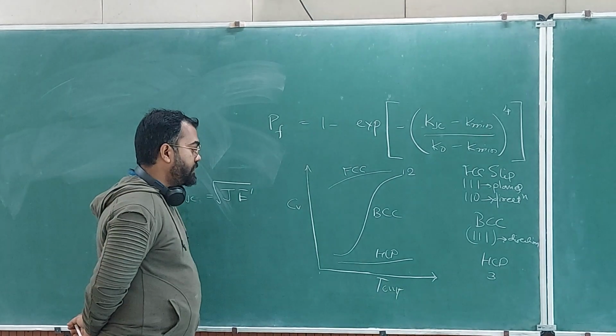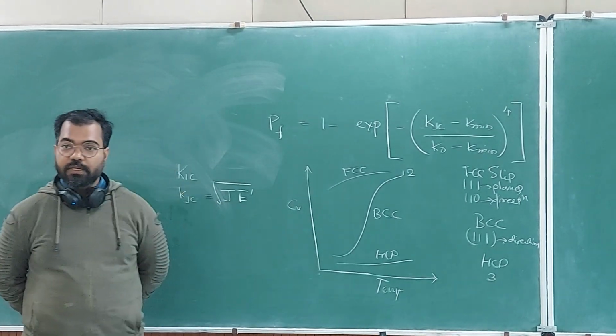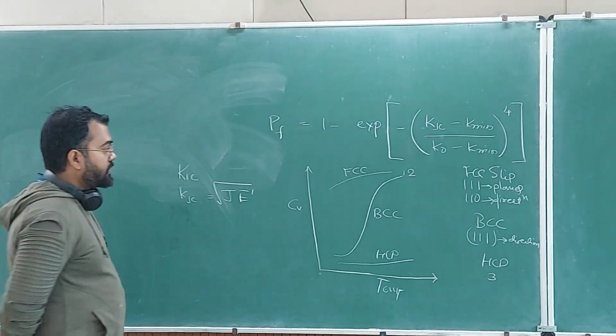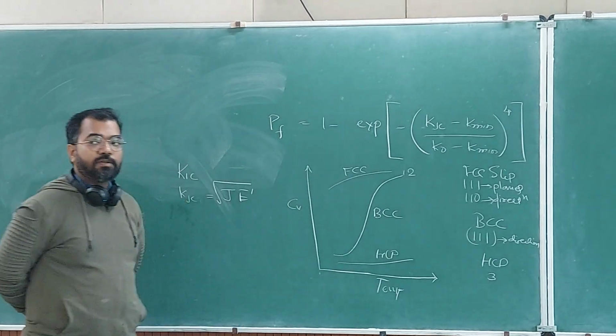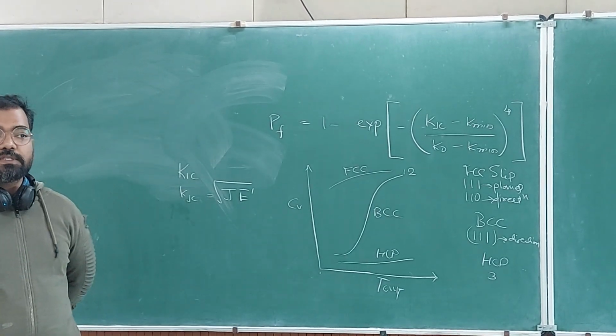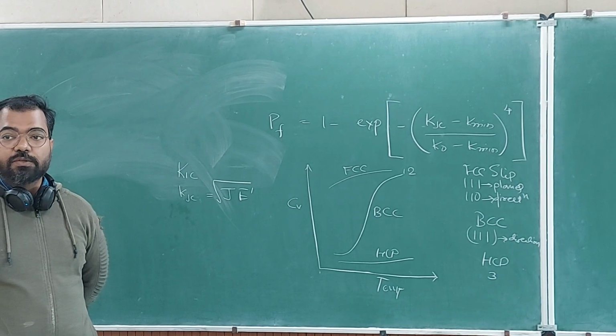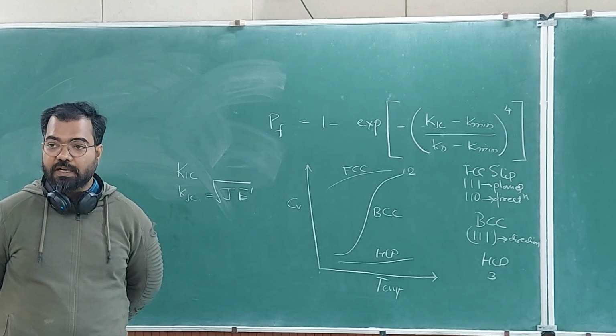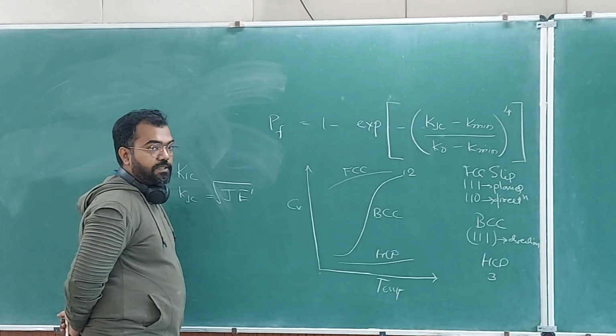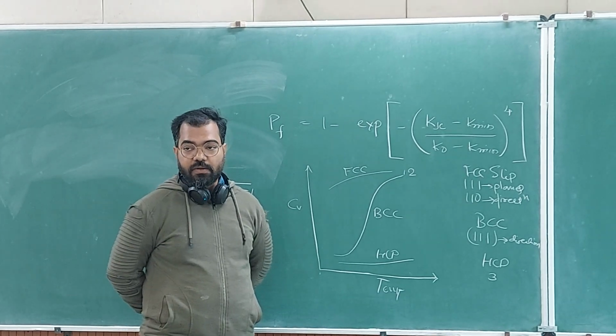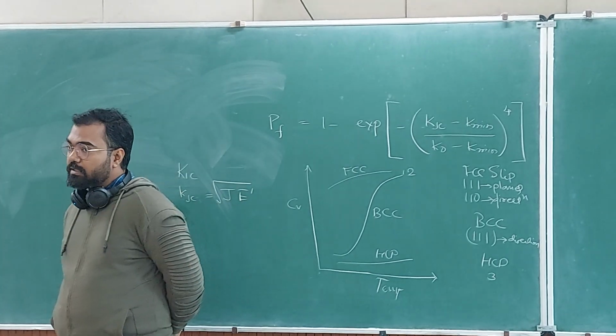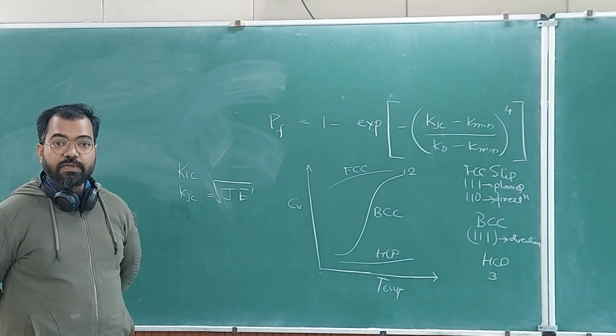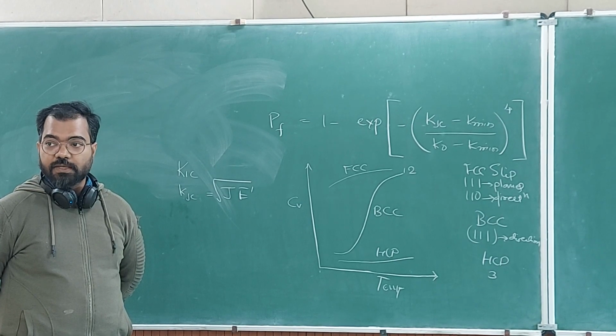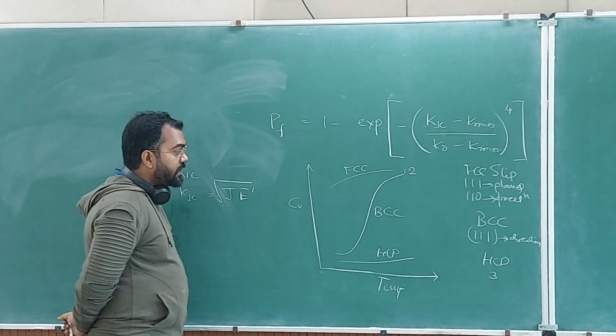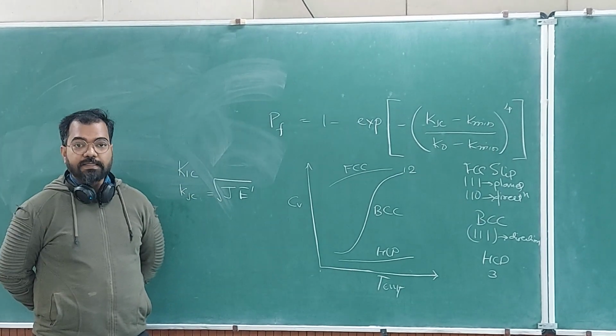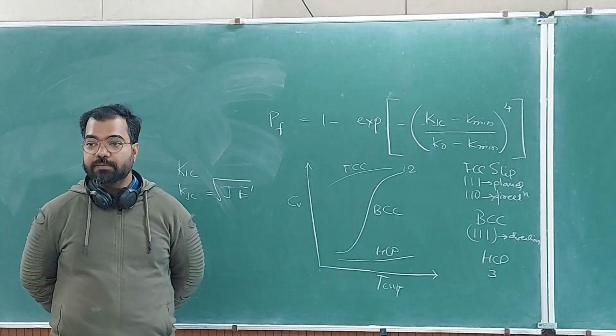And BCC shows a change in energy absorbed from lower temperature to upper temperature. So with temperature, it is not constant, it increases, because it is not just about slip system. Even if you have slip systems, dislocations move when they get blocked. So if you have cross slip happening, if you have a possibility of climb, and these things will increase with increase in temperature, equilibrium number of vacancy will increase. So climb will be possible, and therefore blocked dislocation can move. Okay, so with increase in temperature, you will have enhancement in the toughness of the material, because material will be able to take more deformation. So that you can see in FCC and HCP both. Okay, but in BCC, apart from this, you have a change in slip system with temperatures.